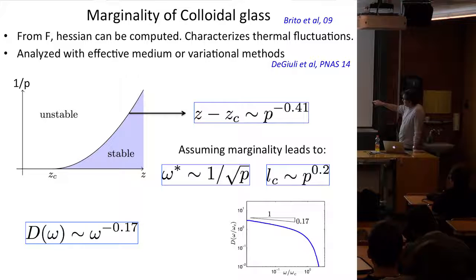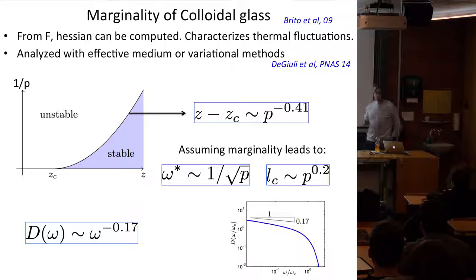And the consequence of living right on this line would be those scaling laws for the frequency scale, for the length scale, and for the density of vibrational modes. So you have non-trivial exponents here, so you can ask how convincing is it numerically? Well, I think, for example, this quantity here, the fact that for hard spheres the density of vibrational modes is not flat like for soft spheres, but slightly tilted, is actually qualitatively observed in numerics, for example. So I think those things are actually true.